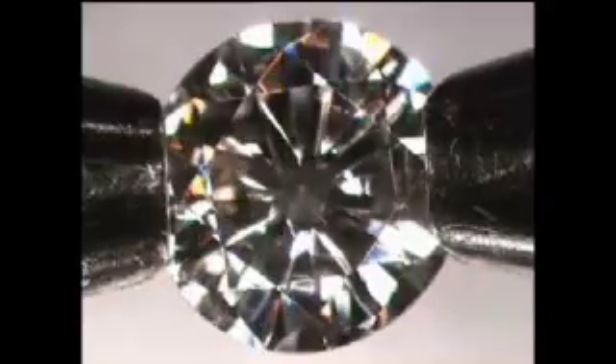When you talk about diamonds and their amazing properties, what other kinds of things can they be used for? Diamond can be the ultimate window material — it's very hard, chemically very inert, and optically transparent. If you put specific defects in diamonds you can use these as potential light-producing centres. There's recent work on diamond single photon sources: a defect in diamond can emit one photon at a time, which you can use for quantum information processing and cryptography. If you send one known photon, you can tell if somebody is intercepting your signal.